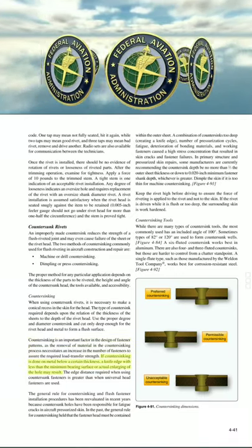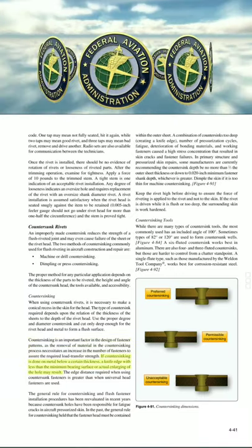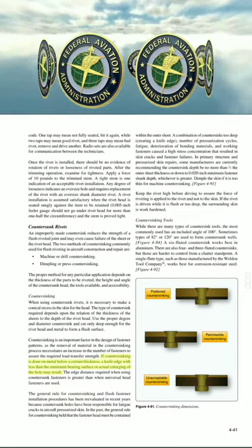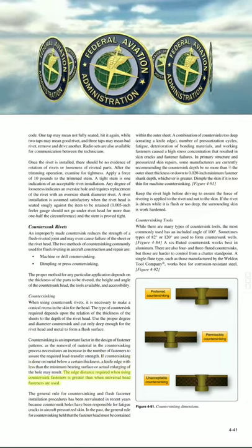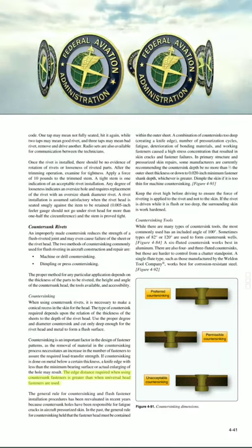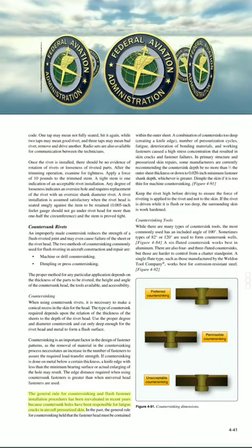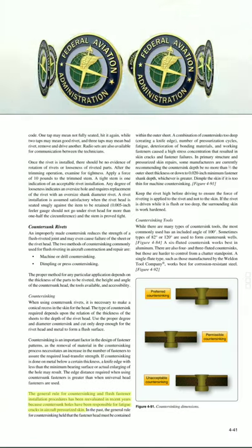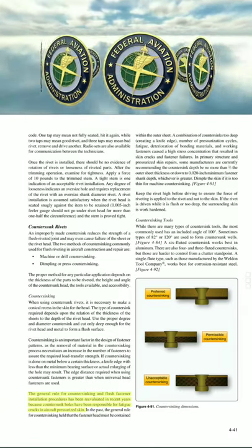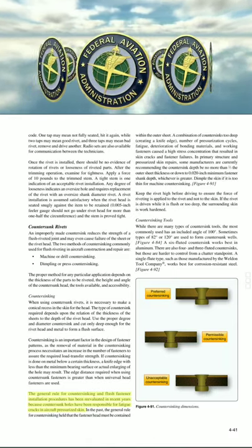If countersinking is done on metal below a certain thickness, a knife edge with less than the minimum bearing surface or actual enlarging of the hole may result. The edge distance required when using countersunk fasteners is greater than when universal head fasteners are used. The general rule for countersinking and flush fastener installation procedures has been reevaluated in recent years because countersunk holes have been responsible for fatigue cracks in aircraft pressurized skin.